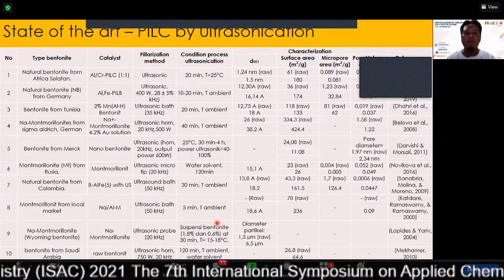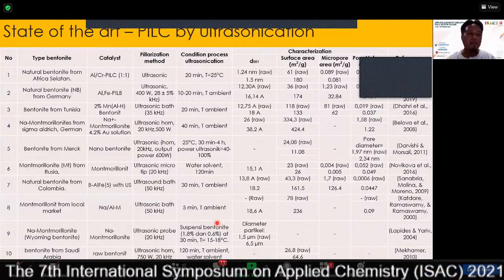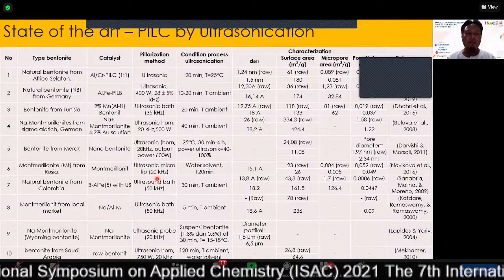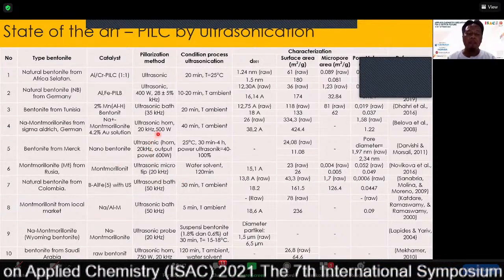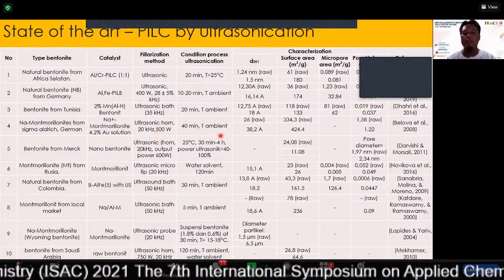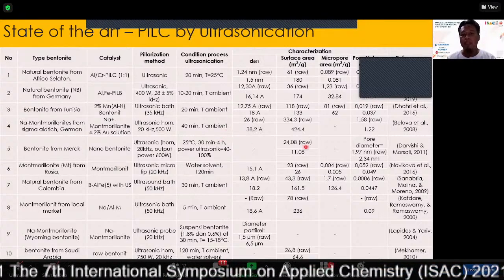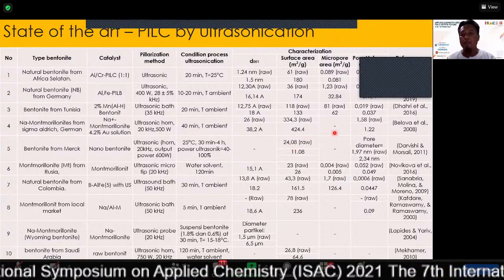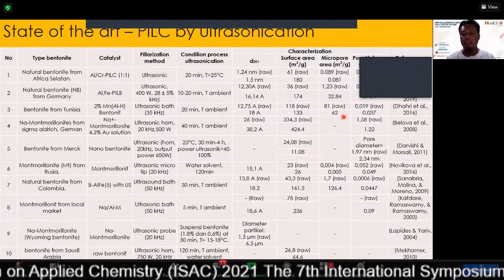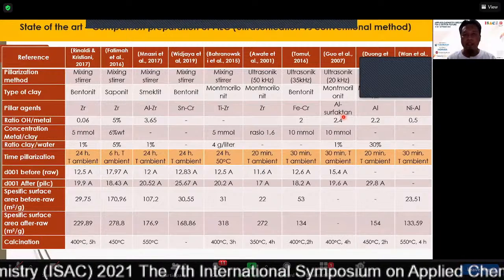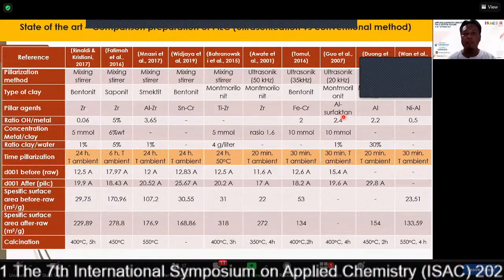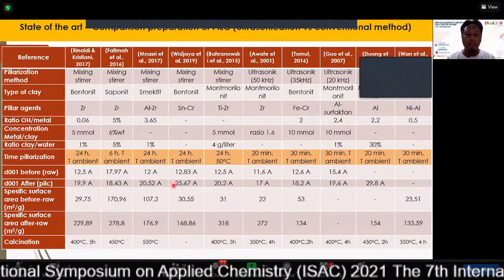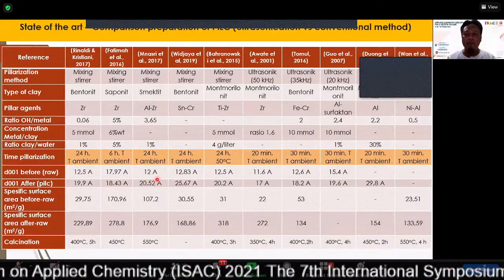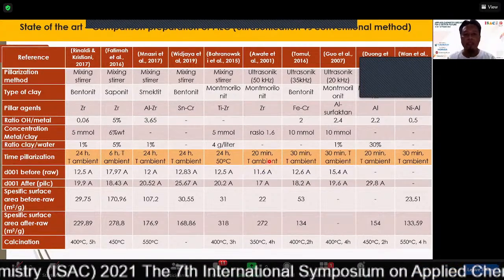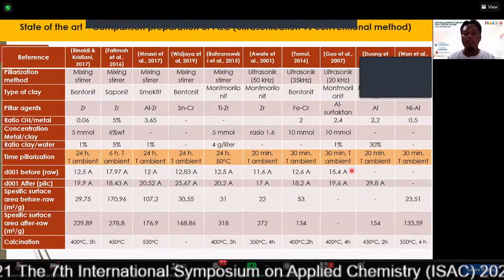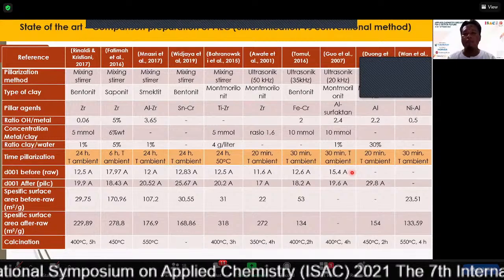This is the comparison of PLC by ultrasonic. You can see number 4, using the ultrasonic horn method, 20 kilohertz, 500 watts, with a condition of 30 minutes and ambient temperature. You can see the catalyst's basal spacing, surface area, and pore volume increase significantly. And this slide describes the comparison of sonication versus the conventional method. You can see the time of synthesis. The conventional method needs 24 hours to form pillars, but the ultrasonic needs 20 to 30 minutes to form pillars